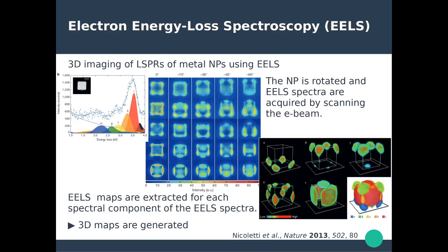For instance, you can see that you have different plasmon modes: some modes exciting mostly the bottom corners of the cube that are in contact with the substrate, while other modes excite predominantly the corners on the opposite side of the substrate, while others excite the edges of the cube and others the faces. This is a very powerful technique developed in 2013 and published in Nature, which allows you to provide very detailed information about the nature of modes in complex plasmonic nanostructures.